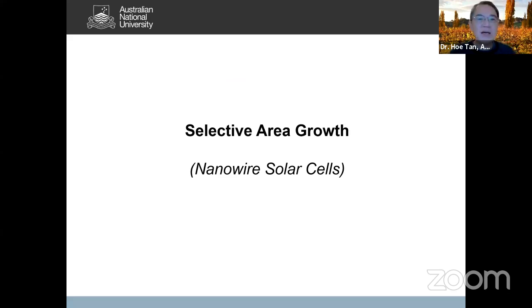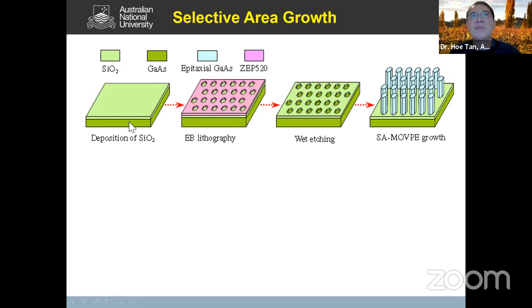Okay, then I'll move on to another growth technique, which is the selective area growth. This is shown here conceptually. We start off with a piece of substrate, for example gallium arsenide or indium phosphide, and we cover that with a thin layer of dielectric, usually silicon dioxide. Then through electron beam lithography, we spin a layer of electron resist and use the electron beam to pattern it. Once we pattern that, we can etch into the silicon dioxide layer to form these holes, then remove the electron resist layer, put this in our growth chamber and start to grow the nanowires. So now you see the nanowire diameter is essentially determined by the hole opening that you pattern.